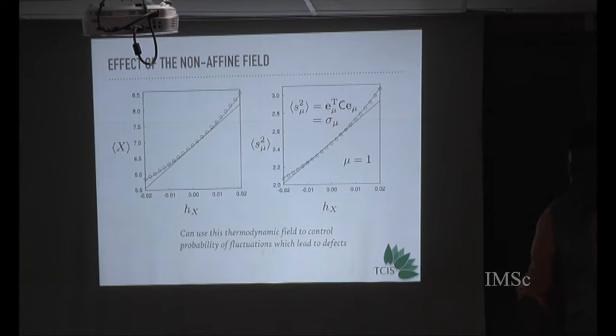Okay. So what happens if you put in a non-affine field? Of course, depending on the sign of non-affineness, you can increase this average non-affine parameter or decrease it. And what that really means is that you can actually use this thermodynamic field to tailor the probability of those fluctuations which are going to cause defects. So it's not directly that you are introducing defects, but you are slightly biasing those displacement fluctuations which will produce defects. And in simulations, this is exactly what it does. So you can control defect density in a colloidal crystal by using this non-affine field. And that has very important consequences.